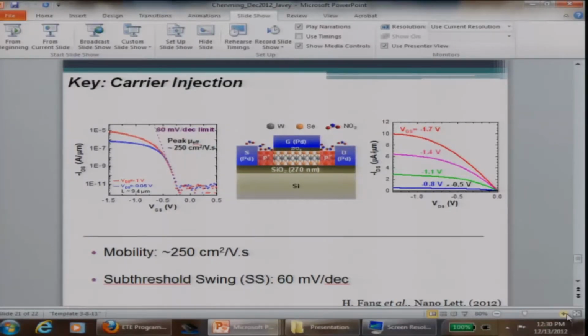We started making self-aligned, heavily doped contacts. This is your tungsten diselenide at the bottom. We fabricated a gate stack on top, zirconium oxide gate, source drain to the left and right. There were underlapped regions. We used the gate as a mask to dope these underlapped regions P+. So now you have source P+, your channel, and the drain.